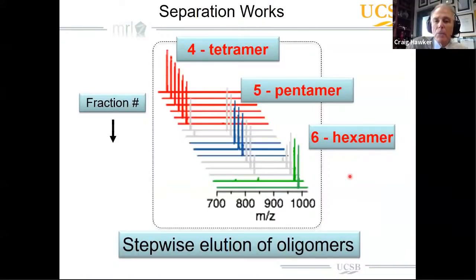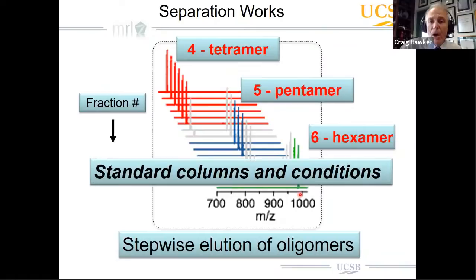And so the idea is very simple. You take that polydispersed mixture and you flow it through your column with the right elution characteristics and elution solvent, and you start collecting fractions. And as I'm showing you here graphically, we have fractions that are pure tetramer, then we transition to a few mixed fractions, and then pure pentamer fractions, mixed fractions, and then pure hexamer fractions. So we have stepwise elution of the oligomers, and the job is to collect each fraction, analyze the fractions, and then decide which fractions to combine.